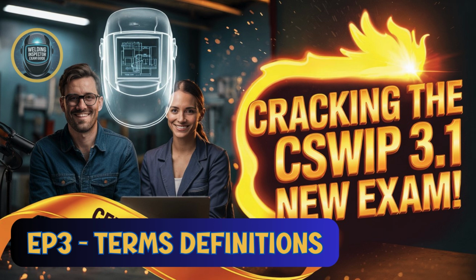And finally, a deep penetration fillet weld. This is a special type where you achieve deeper than normal fusion penetration into the root corner. These are typically produced using high heat input processes like submerged arc welding or maybe MAG welding with spray transfer mode. What's the benefit of that? The main benefit is that you might achieve the required effective throat thickness with less deposited filler metal compared to a standard fillet weld. Less metal can mean reduced residual stress and distortion.